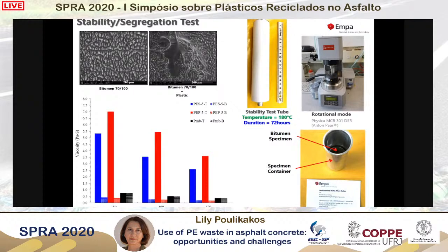Now, we have done some experiments using the stability test, and we looked at the viscosity of the top part of the tube and the bottom part of the tube after this tube was exposed to high temperatures for a certain amount of time according to the standards. And we see, as shown in the bottom diagram, that the top viscosity is much higher than the bottom viscosity. So that shows us that most of the plastics, after the bitumen becomes hot, are moving to the top. And therefore, there's a segregation and a stability problem. This is very important to keep in mind when it comes to storing this material, for example, in a bitumen tank for an extended amount of time.